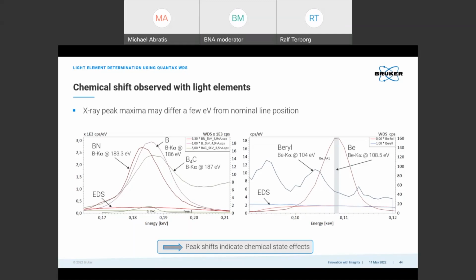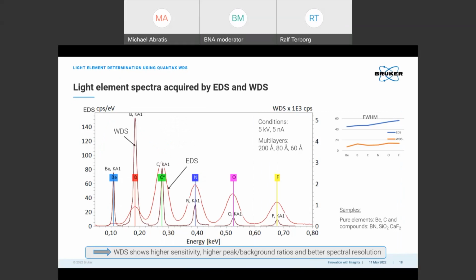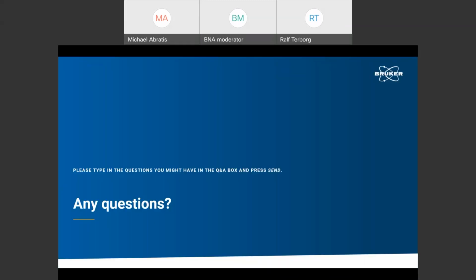Here we present spectra for the light elements from beryllium to fluorine, acquired on pure elements and simple compounds respectively. The spectra were recorded simultaneously with both systems, WDS and EDS. In this chart, EDS spectra are shown in orange, the WDS spectra in darker color. What is obvious is that WDS shows narrower peaks than EDS. Furthermore, we see higher peaks for WDS when we compare the vertical axis on both sides of the graph. This is especially true for the lowest X-ray energies. In conclusion, WDS shows higher sensitivity for the light elements, higher peak-to-background ratios, and better spectral resolution when compared to EDS.